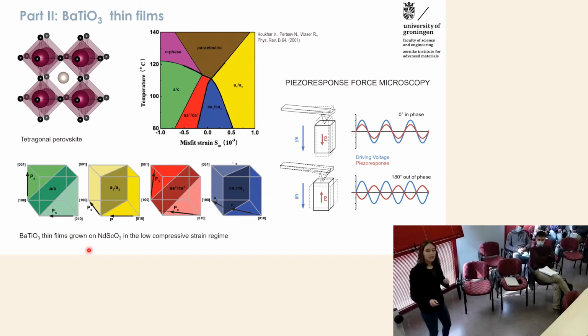So what I mean is that, for example, when we are in a regime of low misfit strain, for example here blue and red, we can have phases where the polarization is pointing in some domains in plane and in some domains out of plane. So this, for example, would be an AC kind of phase. And otherwise, at a lower temperature, we have this other phase where in all the domains, the polarization is always pointing in plane in the film. And this would be the aa-type ferroelectric phase.